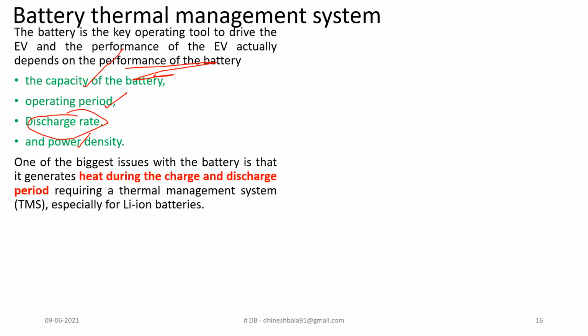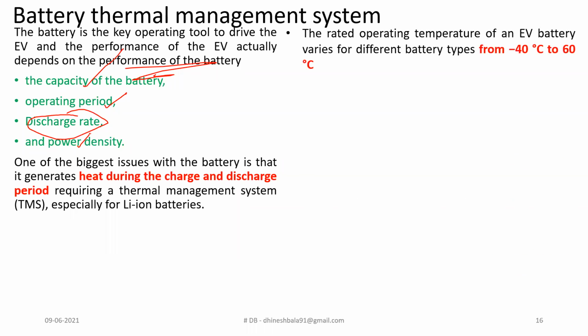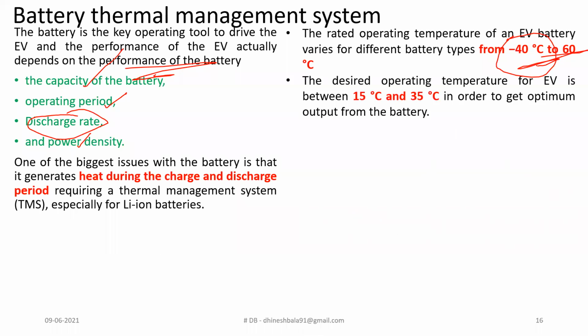It means that the lithium-ion battery, not only the lithium-ion battery, but the battery in general, would generate heat during the charge and discharge period. So this charge and discharge period should be monitored very keenly to maintain the performance of the battery. The operating temperature of an EV varies over a range of -40 degrees Celsius to 60 degrees Celsius. But the desired operating temperature range of an EV is around 15 to 35 degrees Celsius. Your lithium-ion battery would operate at a temperature range of -40 to 60, but the highly desirable condition to get an optimal output lies between 15 and 35.